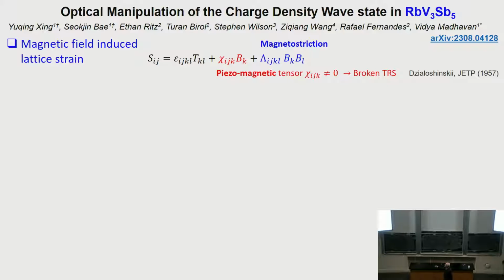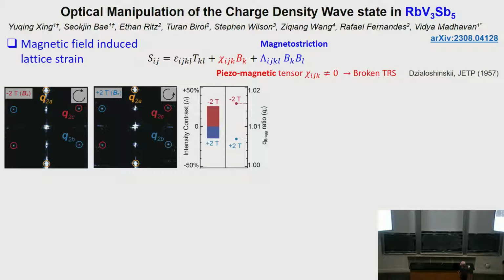And this term is called piezomagnetic response, and the coefficient is the piezomagnetic tensor. If this tensor is non-zero, then the system breaks time reversal symmetry spontaneously. So then magnetic field in one direction versus the other direction will cause different shear strain or lattice distortion. And that would be the way to probe time reversal symmetry breaking.